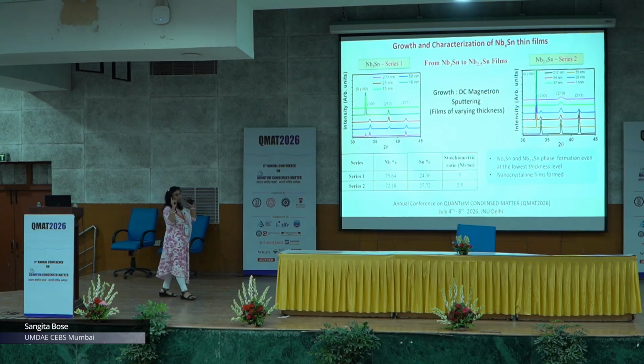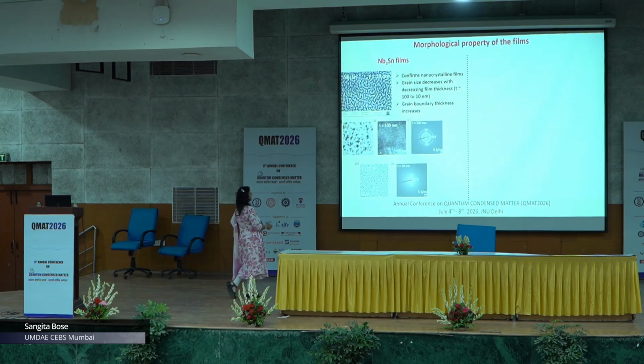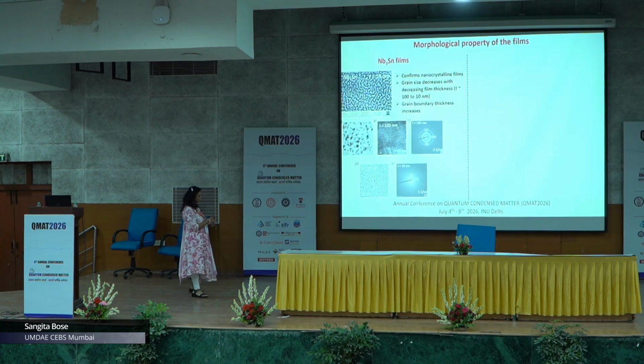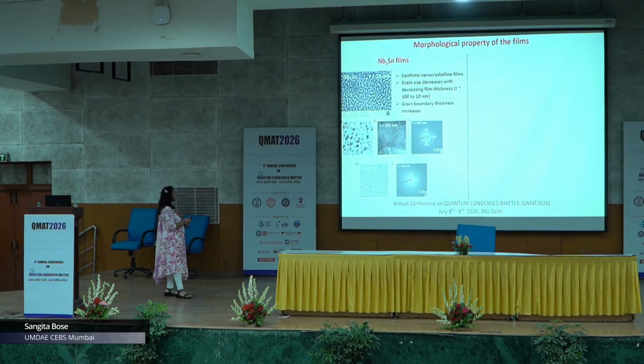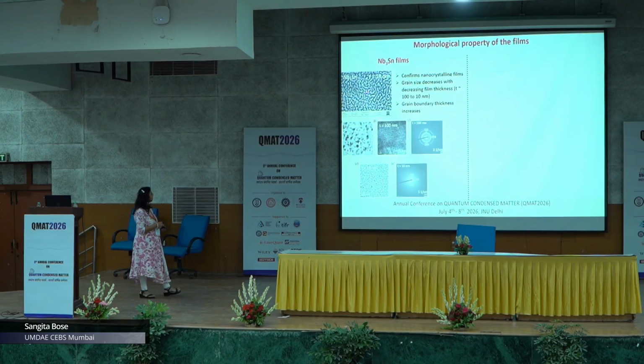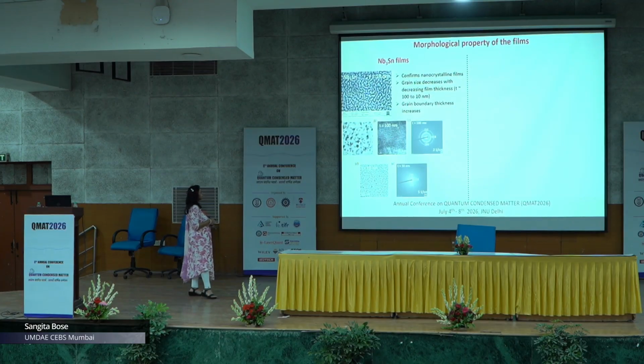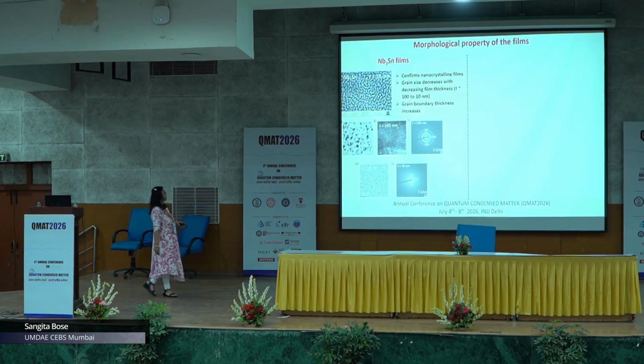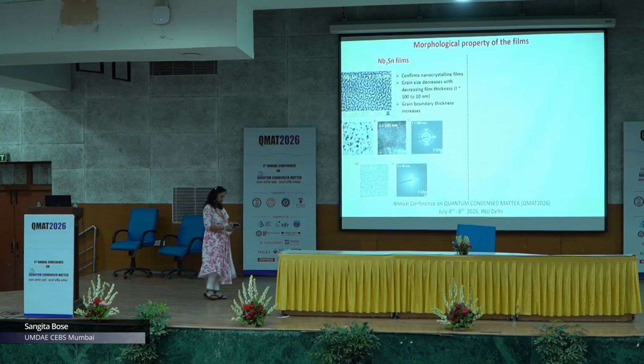So, we have another important thing to worry about, which is the particle size in these systems. If you look at the microstructure, first let us look at how the niobium 3 tin films behave. You can see this is the microstructure for an 18 nanometer film. You can see very small grains, of course, they form clusters like this. The grain size decreases as you decrease the film thickness, a result which we also saw from the XRD. And basically the grain boundary thickness is what increases as you go down in thickness. Of course, we also did some more characterization using TEM to see if we really get these small grains in a 10 nanometer film, and of course, the phase is retained up to the lowest thickness possible.